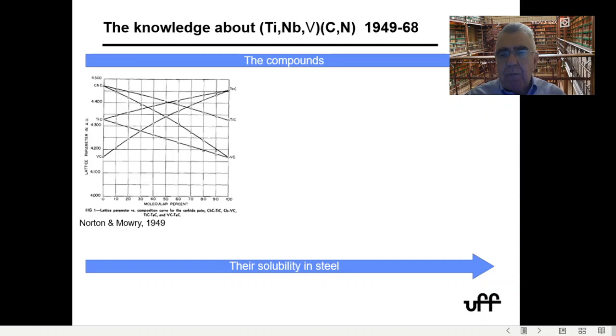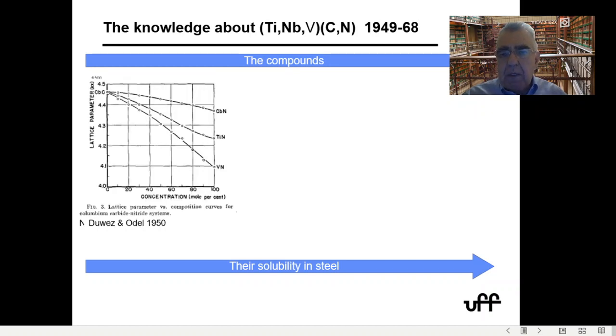The compounds were studied back in the late 40s, early 50s, and you see in this graph that back in 1949 it was already seen that niobium carbide, which is here NbC, and the other carbides had full miscibility. So you can see here the titanium carbide and vanadium carbide, and there was the observation that the miscibility was complete. Later, very close in time, the miscibility between niobium carbide and niobium nitride was observed, as well as with titanium nitride and vanadium nitride.